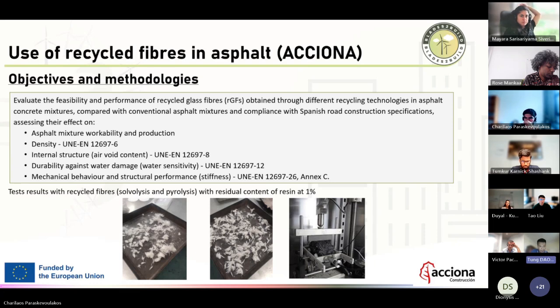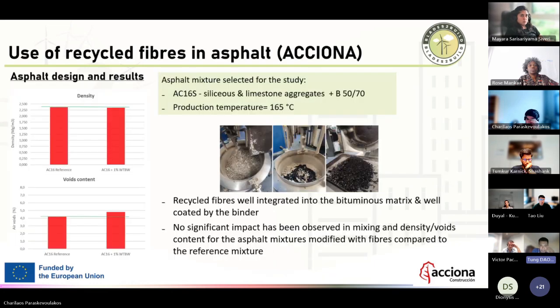They followed a set of tests like workability and production in terms of void content. They followed the density and void content measurement, and then durability against water damage, which is called the water sensitivity. And for sure, they measured the modulus, so the elasticity of the asphalt, according to the normal way that they develop an asphalt recipe. So in the study, they put 1% of the fibers, and they tried to benchmark with the traditional or ordinary asphalt. So please go to the next slide where we can find more details.